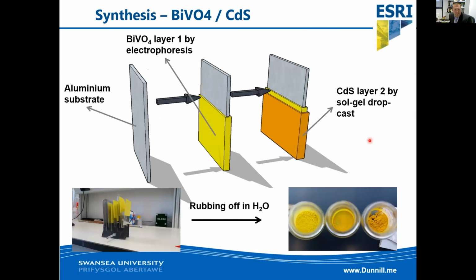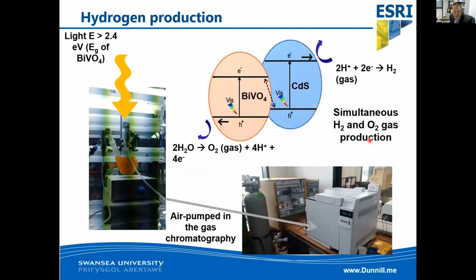Very briefly, this is the bismuth vanadate cadmium sulfide. We can actually put this onto an aluminium substrate. We can use electrophoresis and sol-gel in order to get our samples. And of course, we can end up with our bismuth vanadate cadmium sulfide Janus particles with the Z-scheme system set up. So we can take in 2 visible light photons and we can actually split water with that, using the experimental setup and gas chromatography.